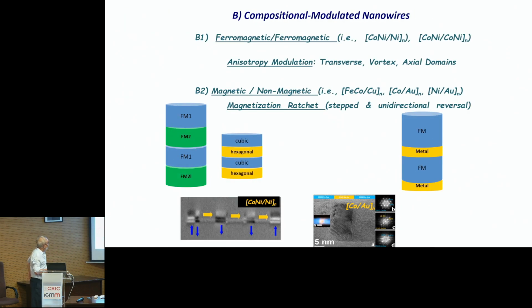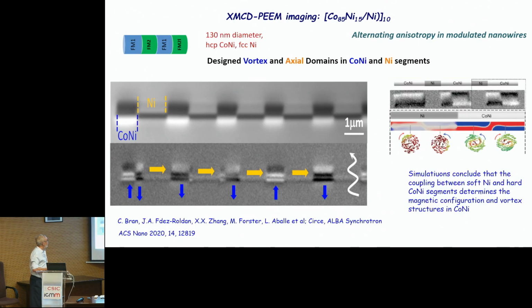And the very, very last part, so it's my minute 10, is about the compositional modulated nanowires. There are two types of compositions. One is ferromagnetic 1, ferromagnetic 2, having cubic and hexagonal crystalline structure to obtain a modulation in magnetocrystalline anisotropy. And the other family is ferromagnetic and metal. So two magnetic segments separated by a metal. So these images were obtained in a cobalt nickel multi-segmented nanowire. So both are magnetic, but one is hexagonal and the other is cubic.